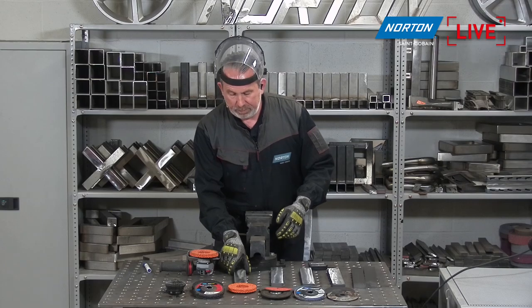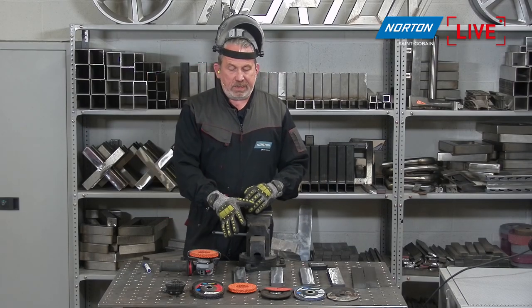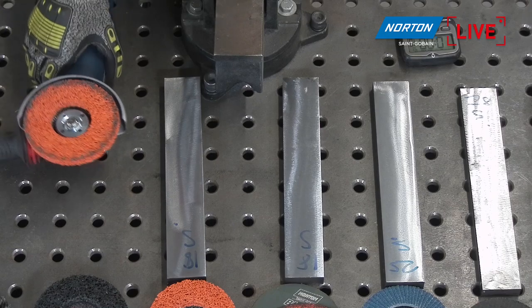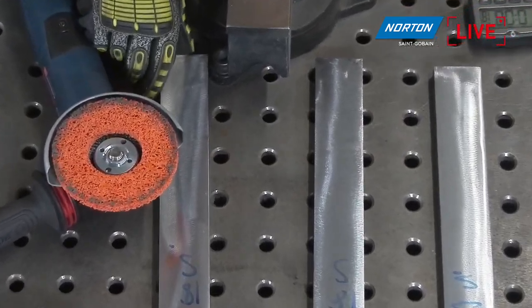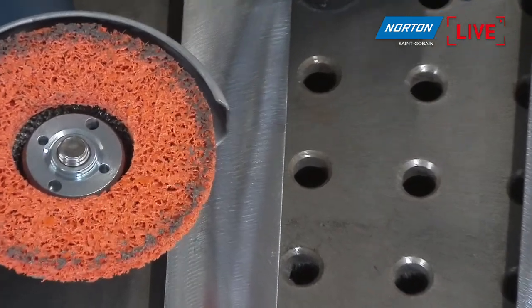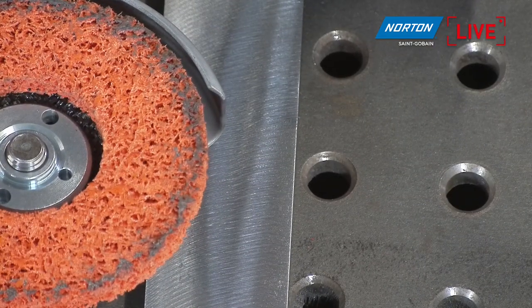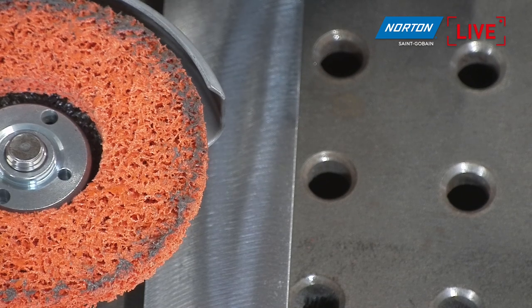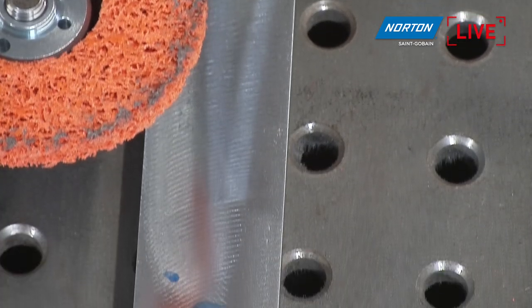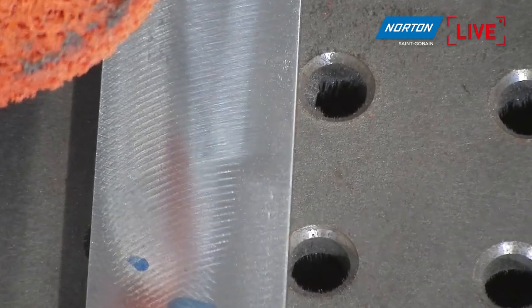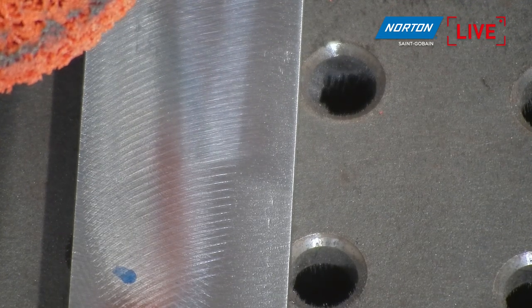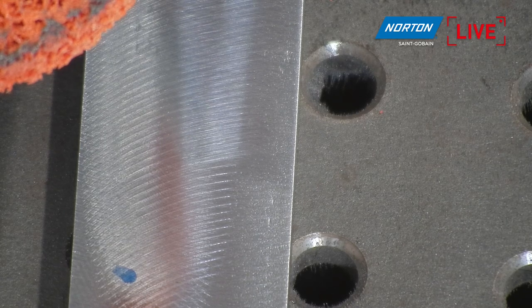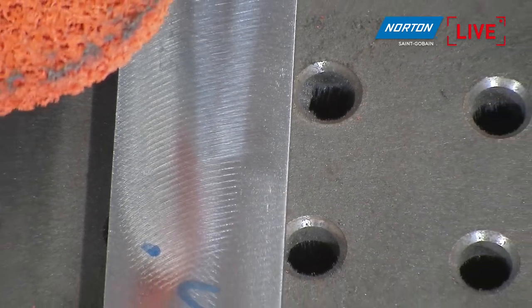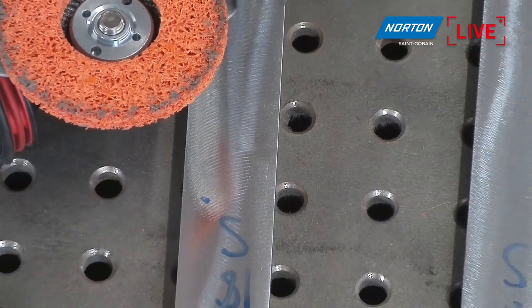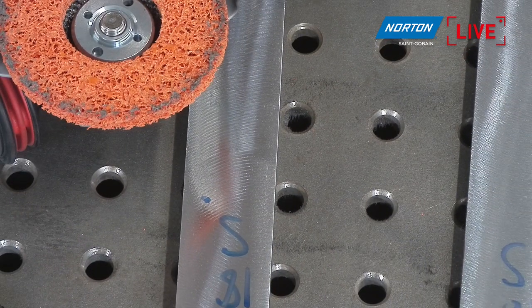Exactly, that's a really good point raised there, Robin. So 18 seconds, same speed as the Blaze fiber. But I think you can see on this picture, the finish is just that bit better than any of the products so far. It's nice, it's flat. And as Robin just alluded to, this scratch we've left behind is absolutely perfect finish for paint. So you'll be able to paint this with powder coat or spray paint. The paint has a key to adhere to the surface, which is really important. You can't paint polished steel because it will just chip off very quickly. You need a scratch to be able to get the paint to stick on.